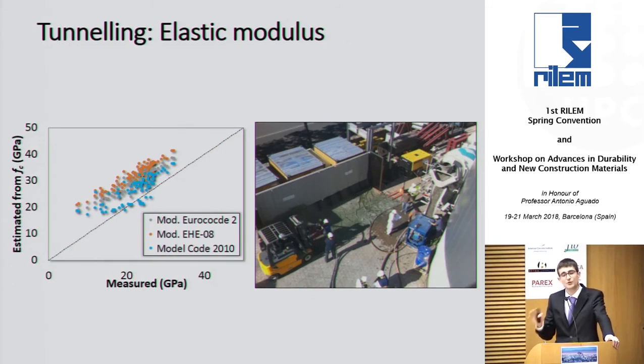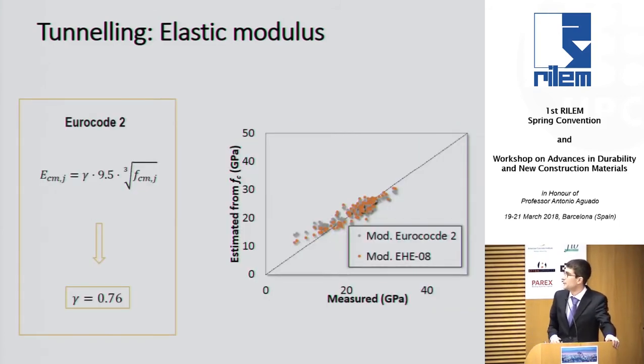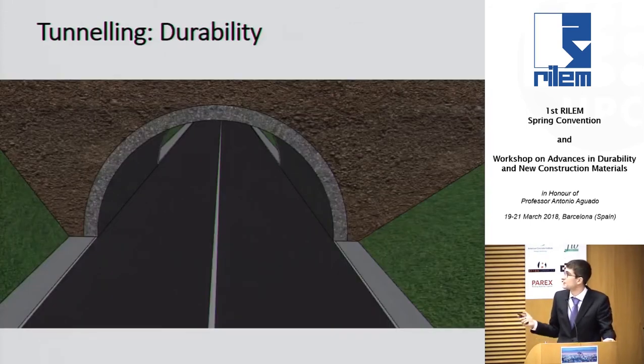And this also happened in other properties, like shear. It happened in bond with reinforcement. So the same was observed in many areas. But the good news is that it's easy to adapt, right? The formulation that we have, here, for instance, the Eurocode 2 formulation, we can easily adapt for this type of material to get a better adjustment between the measured value and what we can find using the simplified equations from the codes. So it's a good thing, right?